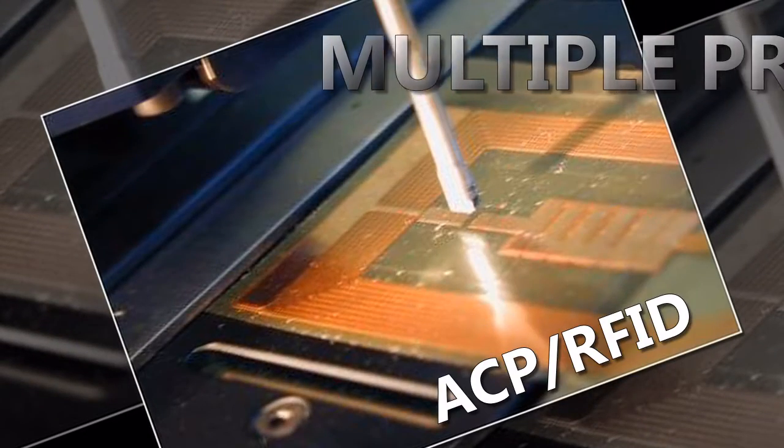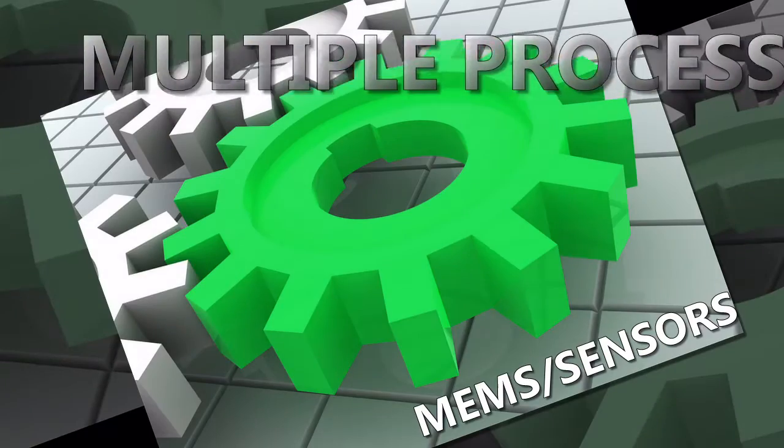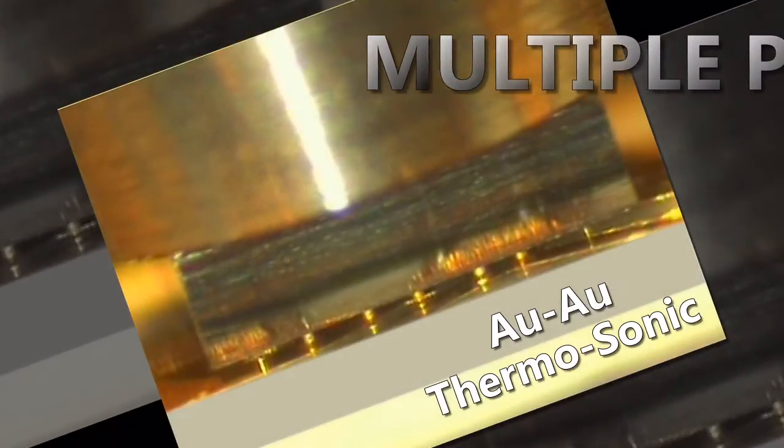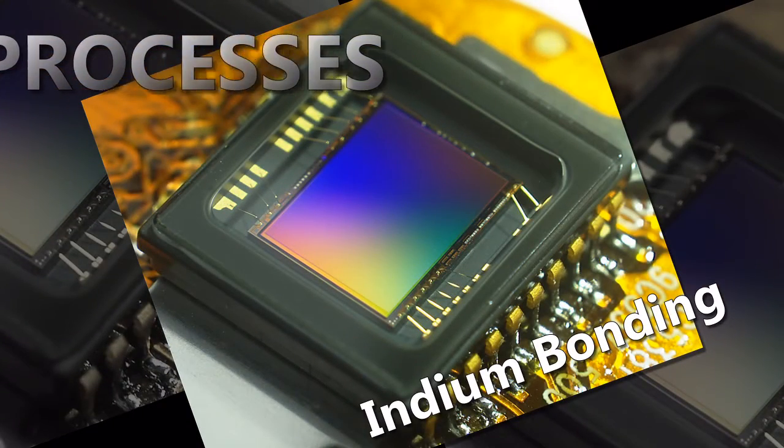Anisotropic conductive materials for RFID, MEMS, and sensor bonding technologies often utilize a dispensed medium. Thermasonic bonding of gold stud bump die is a low-temperature process, whereas eutectic gold-tin laser bar bonding and indium bump die require higher temperatures and a reducing environment.